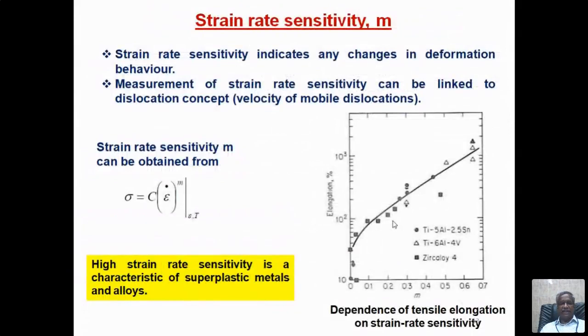And strain rate sensitivity is another parameter which is very important. Strain rate sensitivity indicates any changes in deformation behavior. Measurement of strain rate sensitivity can be linked to the dislocation concept. It is related to the velocity of mobile dislocations, and it is given by this equation: sigma equals C into strain rate power m.